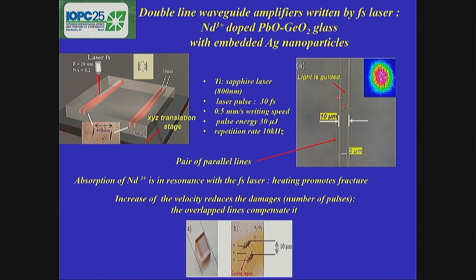And now I will move to the results obtained with the femtosecond laser irradiation. All these experiments were performed in collaboration with Centro de Lasers e Aplicações, do IPEN, located at IPEN, São Paulo. Here I show you the setup we used. The sample is placed in this 3D translation stage that is perpendicular to this laser. It's a titanium sapphire laser that operates at about 800 nanometers, delivering pulses of 30 femtoseconds.